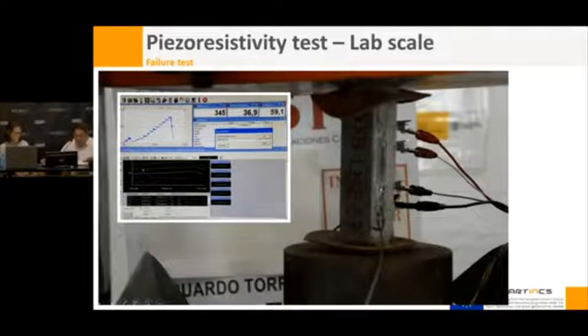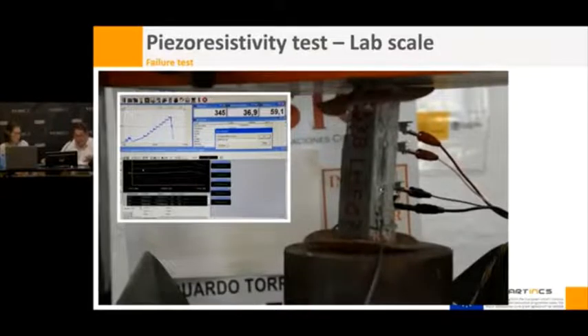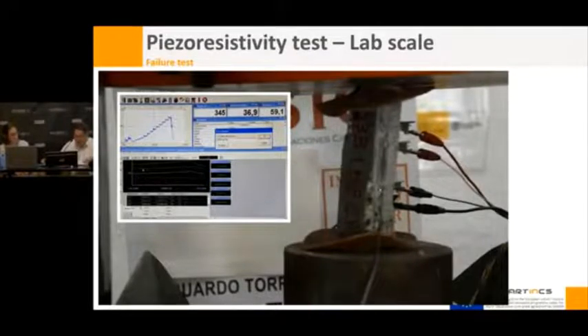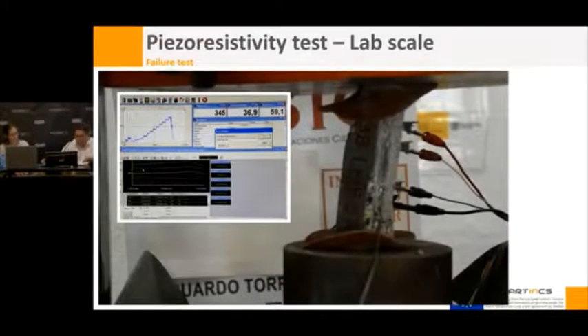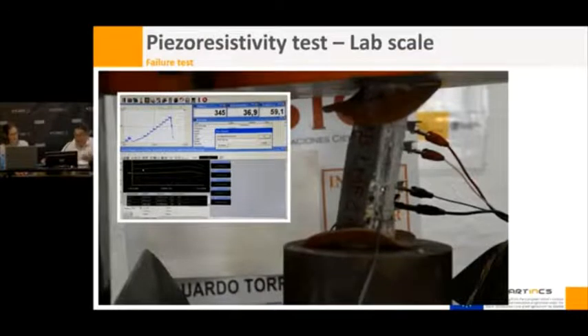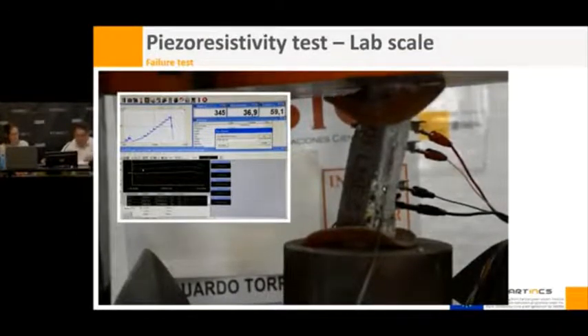No sign related to the self-sensing properties that could anticipate the failure of the material is clearly observed during the failure, and we cannot know the value of the characteristic strain of the material beforehand. We can observe some results related to the stress deformation when the load exceeds the elastic zone of the material, possibly a consequence of a permanent deformation or permanent damage. It is an interesting line of research to continue into the future.